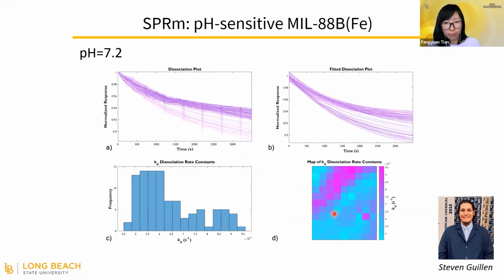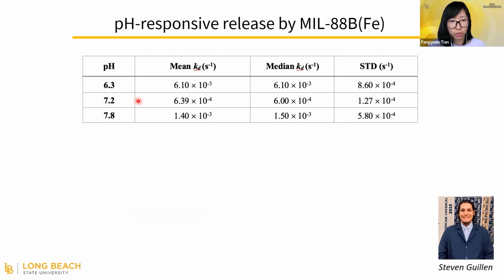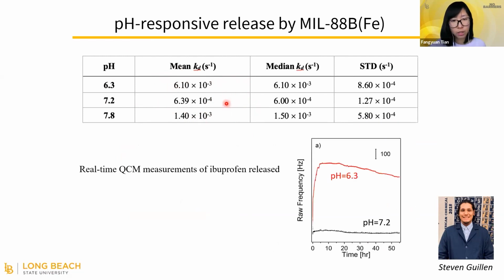Here we can look at the mapping of the whole surface. This is a pretty big area, like 20 by 20 micrometers. You'll notice that a higher pink color means we have more crystals there. We summarize all of the data here under the different pH conditions. We notice that in a more acidic condition, the decomposing or dissociation rate is about 10 times higher compared to neutral condition. And that's exactly what we observed for drug delivery, using the QCM to look at the real-time, in situ drug release process. When the PBS solution is at pH 6.3, you'll notice that the dropping of mass or the frequency is much deeper, meaning more drug is released compared to the neutral condition.